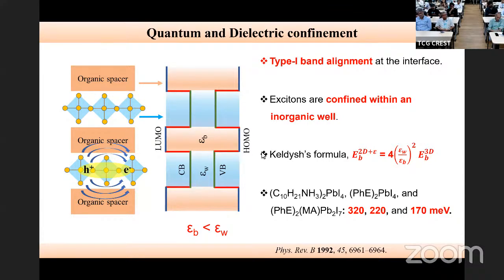That's only hydrogen bonding. So all the electronic structure of this inorganic unit in the 3D case was 3-dimensionally delocalized. But now it will get 2-dimensionally delocalized. And in a third dimension, it will get quantum confined. The moment you quantum confine the system, the band gaps will increase because of quantum confinement. And band gap is a very important criterion for all the applications that I'm talking about. And if my band gap increases in an uncontrolled manner, then that is the price that I'm paying. Not only that the band gap will increase, now that the dielectric confinement is there, because this has a very different dielectric constant than that one, electron and hole will only be able to delocalize in 2 dimensions rather than in 3 dimensions. Therefore, the excitonic binding energy, which goes as 1 over epsilon squared, will be increasing significantly.